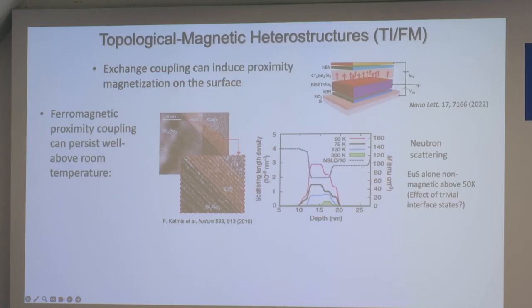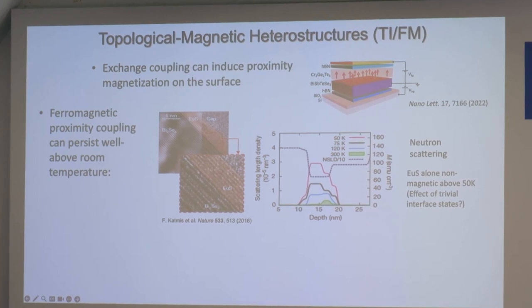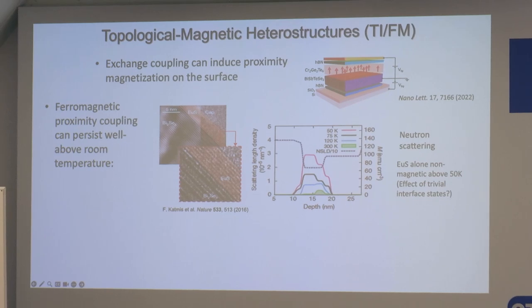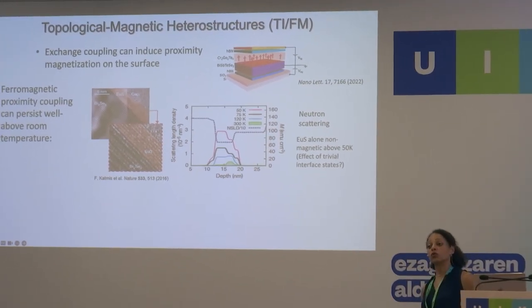And this is promising because of previous experiments, which have shown that you can induce a very good proximity magnetization on the surface just by exchange coupling. So it's just an exchange coupling between the magnet and the topological surface, and you can clearly induce magnetism in the surface state that way. And this sort of ferromagnetic coupling can persist to room temperature.